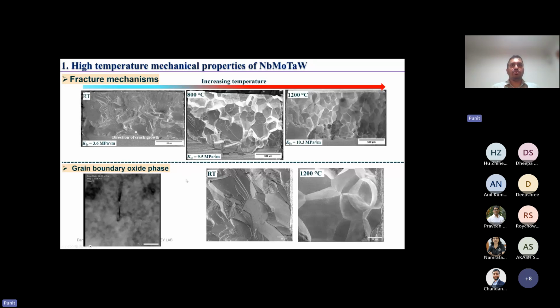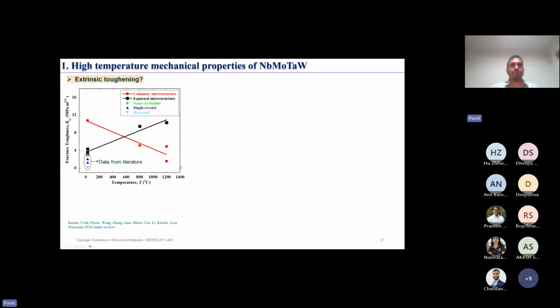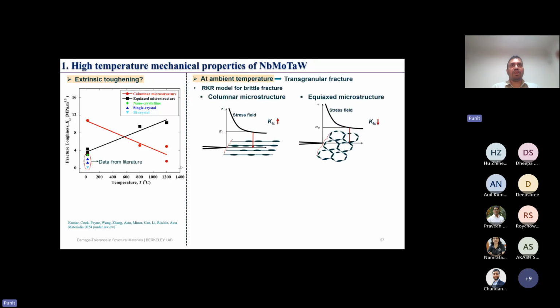And it is also known that these oxide phases, niobium pentoxide phase, go through a polymorphic change at about 800 degrees C, and by around 1200 to 1300 degrees C is when they melt. So this indicates the reason for this interesting change in the mechanism of fracture. Although we were able to understand what is going on with the fracture surface, we still wanted to rationalize the reason for the differences in the fracture toughness values.